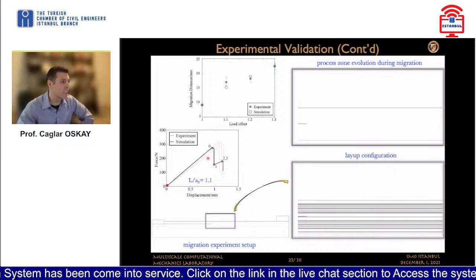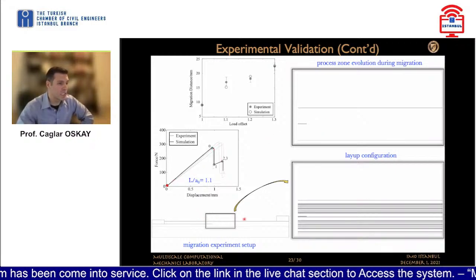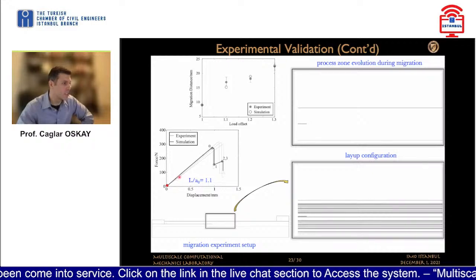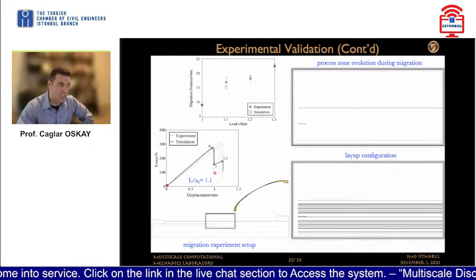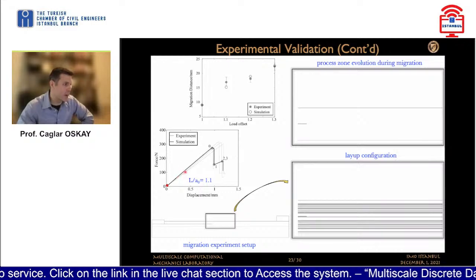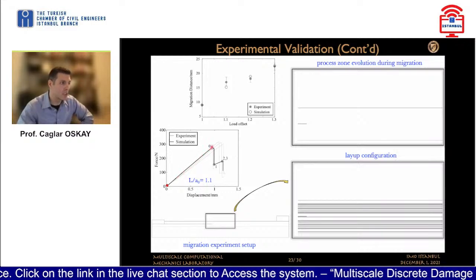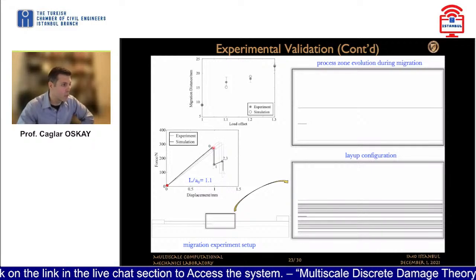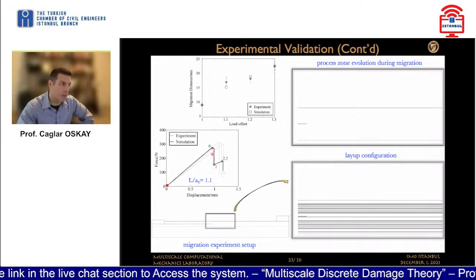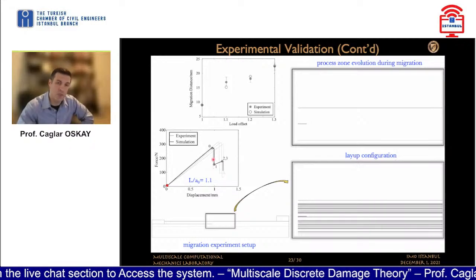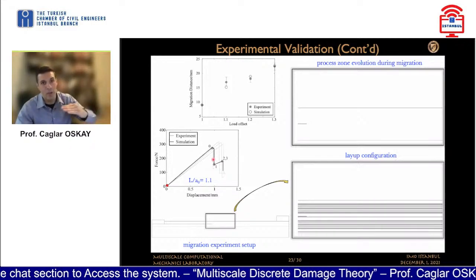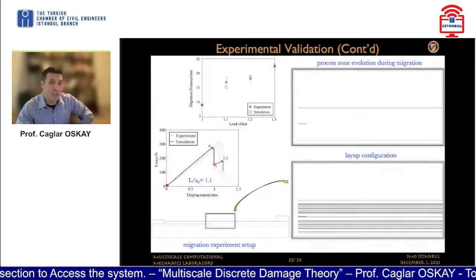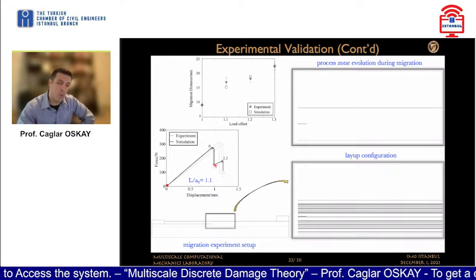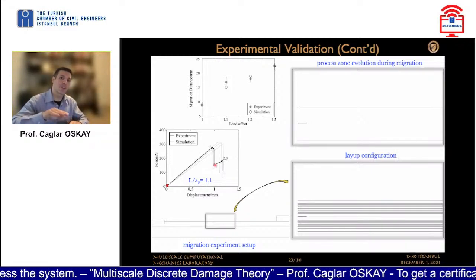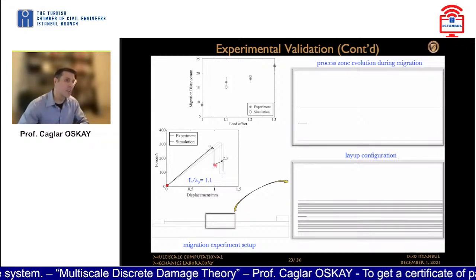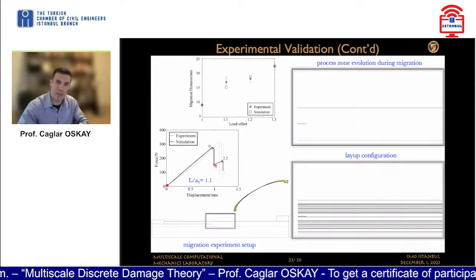So what we are seeing here are some simulations, and a discussion of how the fracture propagates. You're going to see that the fracture will not propagate until you get to the strength of the lamina. Then we go down the force displacement curve, during which the delamination propagation occurs. Then we hit point 1, after which the material starts to gain a little bit of strength again. During that time, a fracture process zone forms.